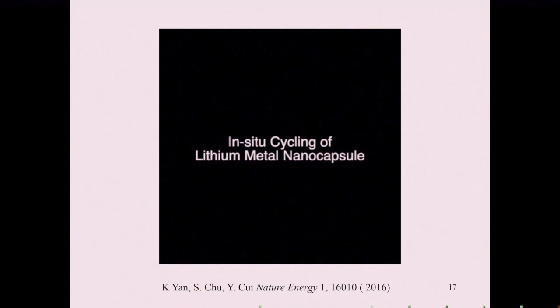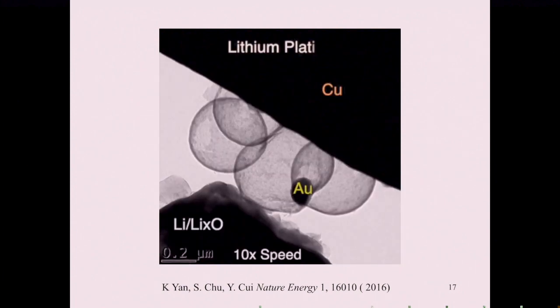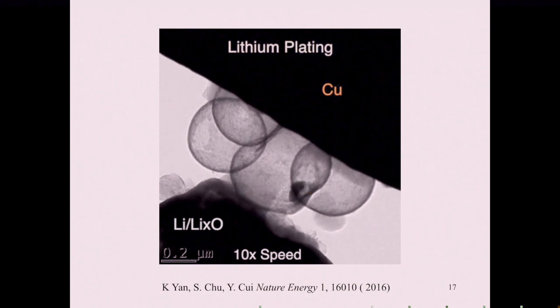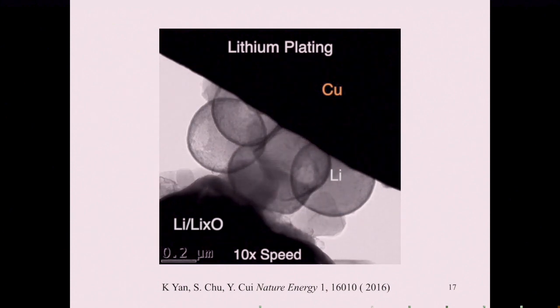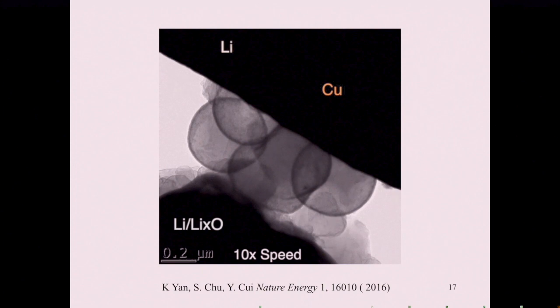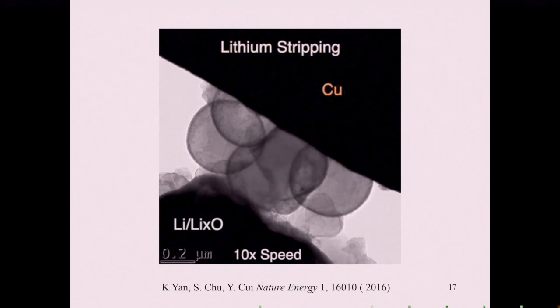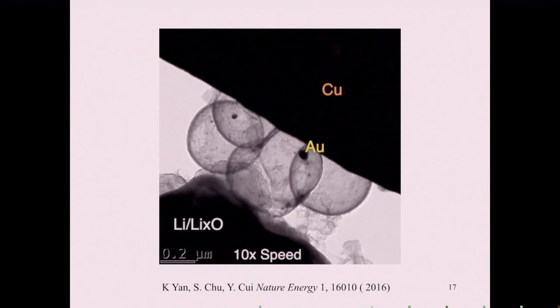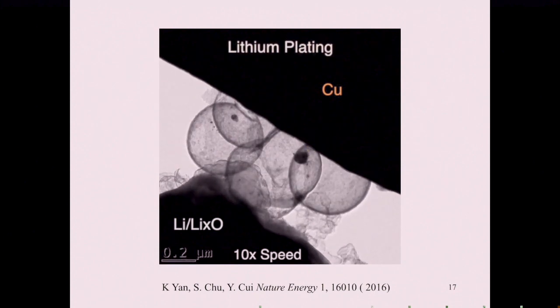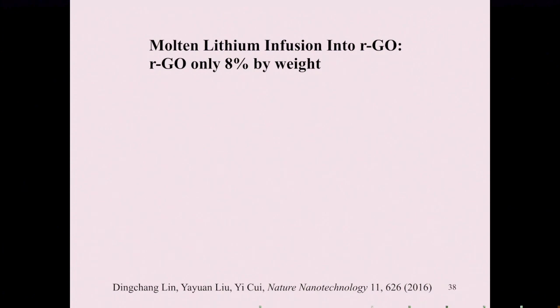This is the video. We have hollow carbon right here. This is a gold nanoparticle. Now we put lithium in. You can see gold functions as the seed, and it actually gets dissolved away in metallic lithium and promotes the lithium deposition going inside of this hollow carbon sphere instead of outside. So using an idea like this, we can really understand how the lithium plating is taking place. Once lithium gets extracted out, this gold particle comes back. With a structure like this as a new host, we could now stabilize metallic lithium deposition a lot more.